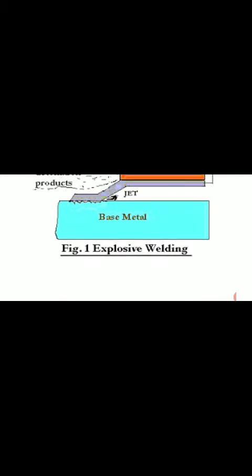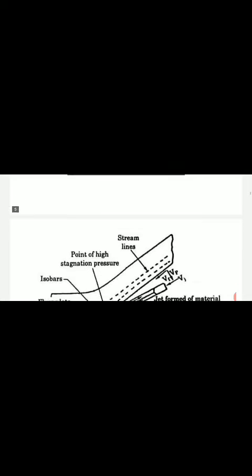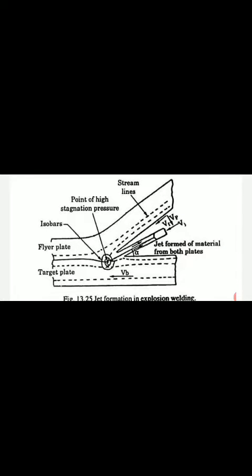Then coming to the concept behind this: under the impact of explosion, the flyer plate collapses, and at the point of impact between the flyer plate and the target, a high fluid pressure between 70 to 700 kg force per centimeter square is generated.